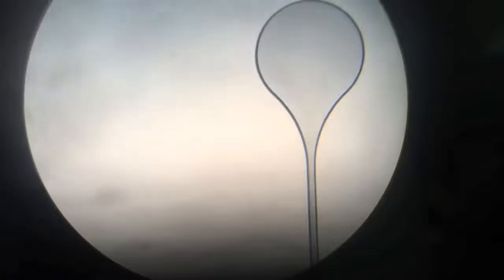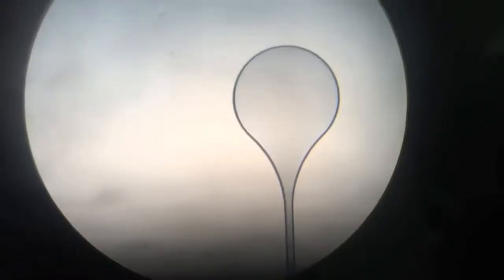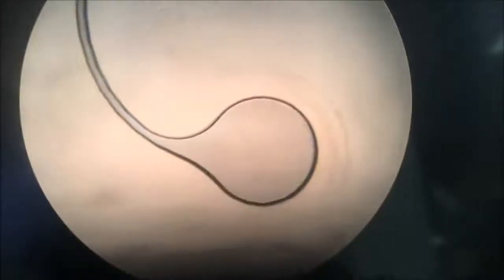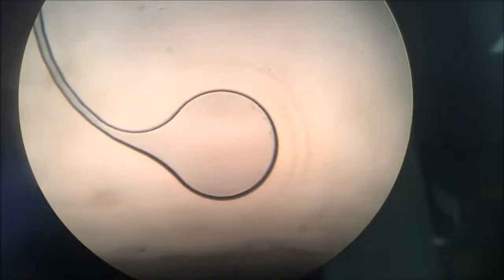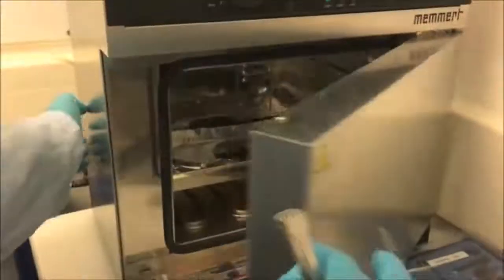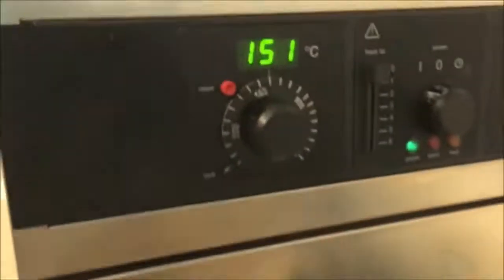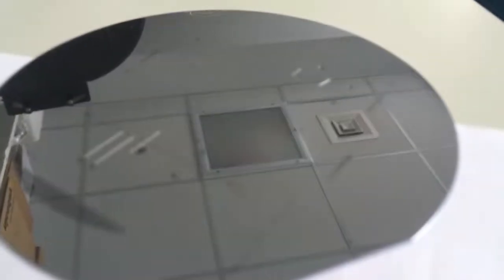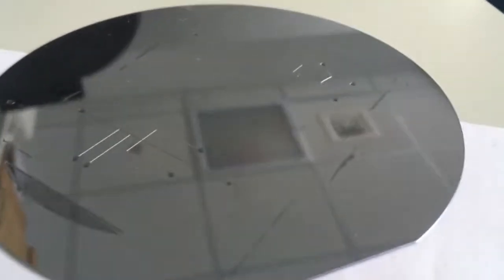Check the channels under a microscope. Look for wall quality and any defects and blockages. You may see crack formation in the channel, particularly at corners and junctions. These can be removed by hard baking at 150 degrees Celsius for 5 minutes. Now you have your silicon master wafer ready to create your PDMS device.